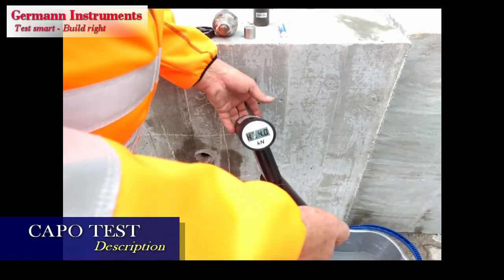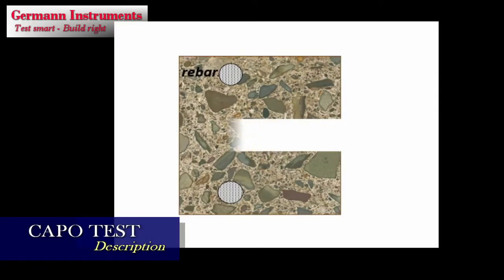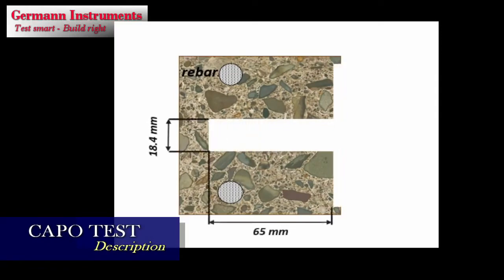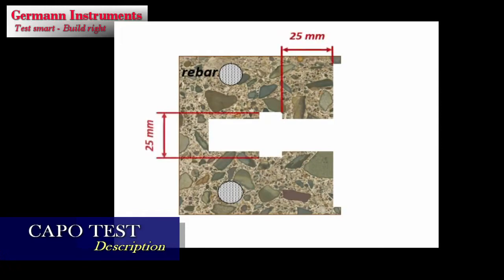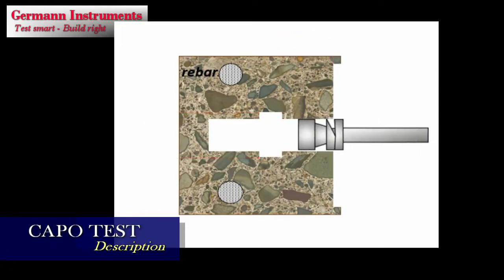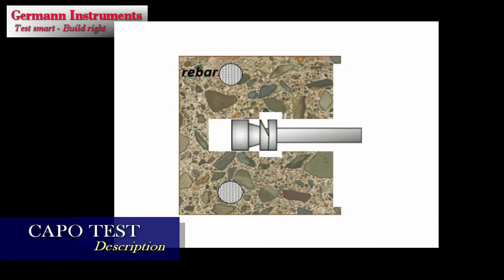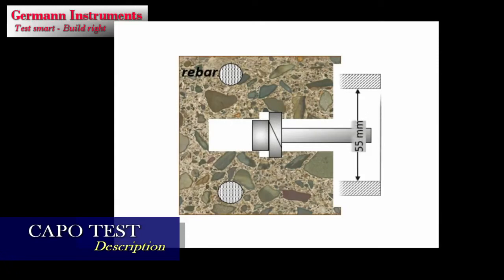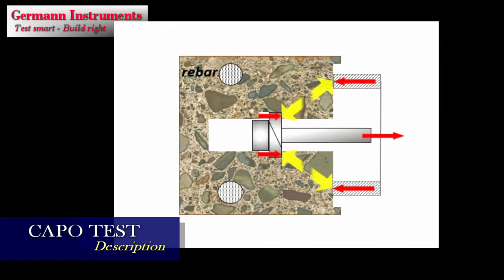Performing the CAPO-Test starts out with coring a hole, 18.4 mm in diameter, 65 mm deep, then the surface is planed, and a recess 25 mm deep is routed, 25 mm in diameter. An expansion tool with a folded steel ring is inserted in the cored hole and expanded in the recess to 25 mm diameter. The pull bolt is coupled to a precision hydraulic pull machine and loaded to failure of the concrete between the expanded ring and a counterpressure, 55 mm inner diameter, placed centrally on the surface.